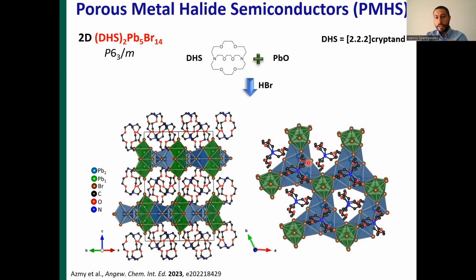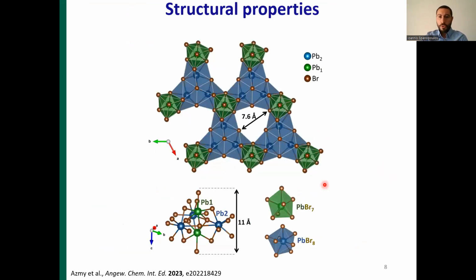The organic ligands are arranged in a hexagonal motif, which is templated by the protruding lead bromide clusters. So let's have a closer look at the inorganic layer of the structure. This is part of the inorganic layer. This inorganic layer consists of lead bromide clusters, and each cluster consists of 2 lead bromide 7 capped trigonal prisms and 3 lead bromide 8 endecahedra.